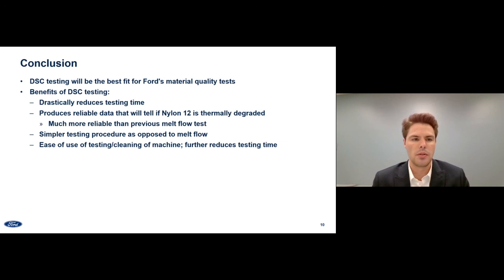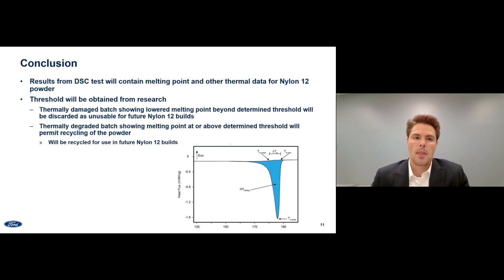In addition, the DSC will produce very reliable data that will show if nylon 12 is thermally degraded and is much more reliable than the melt flow machine used previously. Along with that, a standardized and simpler testing procedure will contribute to producing more reliable data using the DSC, and it will be easy for the operators of the testing apparatus to conduct tests. Also, the results that Ford will be keeping from DSC testing will contain melting point and enthalpy of melting from the DSC charts that will be obtained through testing.